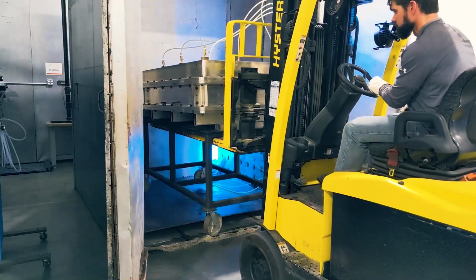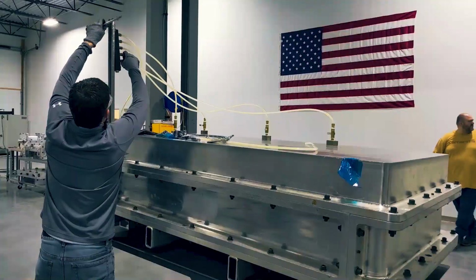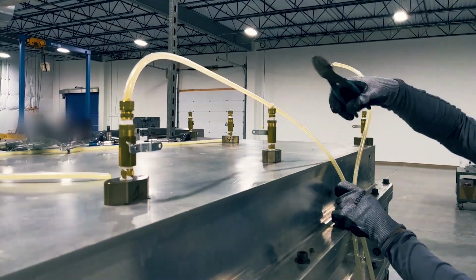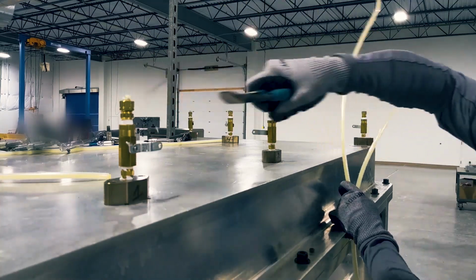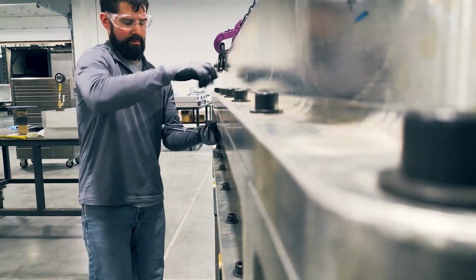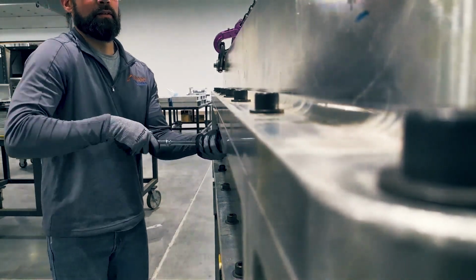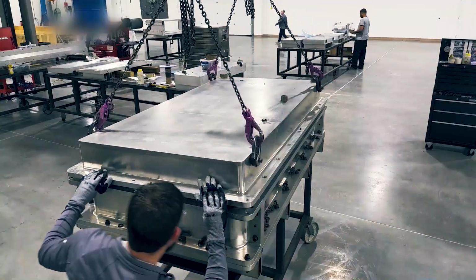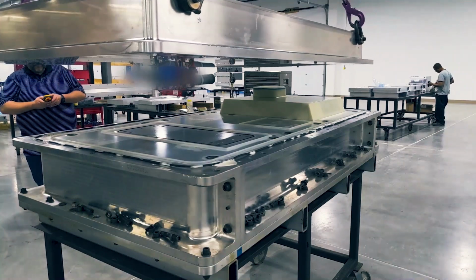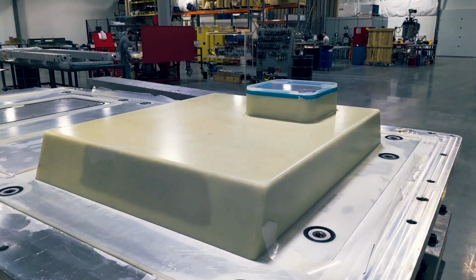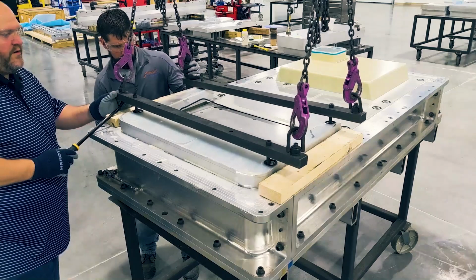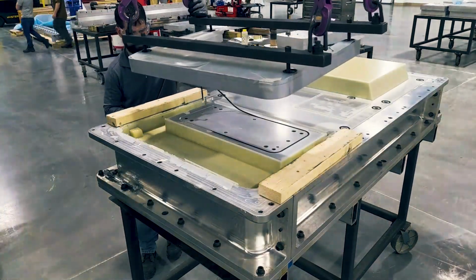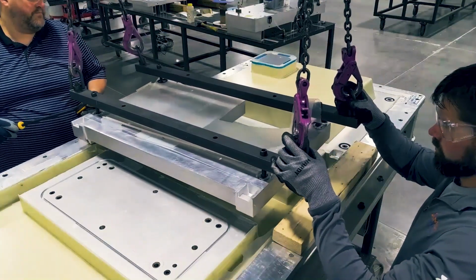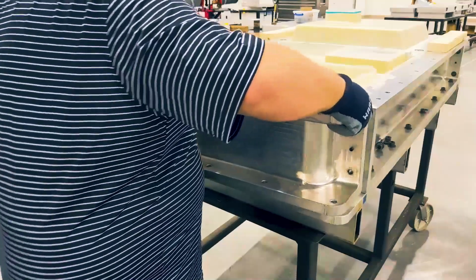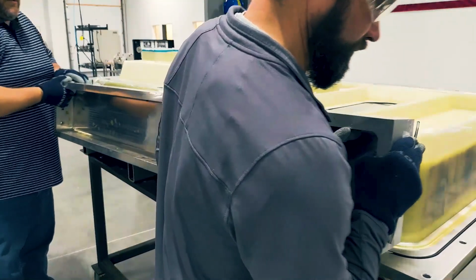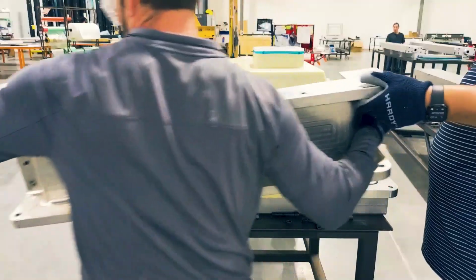After cure, the mold is removed from the oven. The inlet tubes are removed, and the mold is opened in steps. First, the match tooling is removed, releasing the trapped parts of the composite, and then the outer tooling is removed. The requirements for minimal draft required the design of a complex mold that worked as expected.